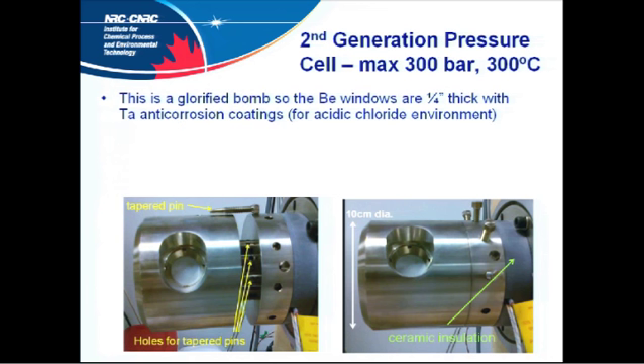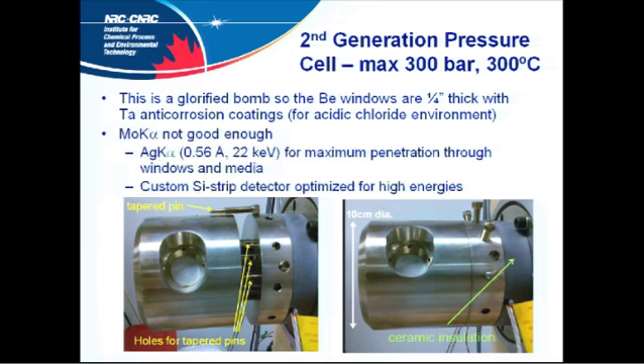Now, this, as I say, is a glorified bomb. This is a new one. 300 bar, 300 degrees. This thing's heavy. This is where you start getting into size and weight constraints. This thing's about 10 kilograms as a full thing. So there's actually quite a lot of weight hanging off here. Moly's not good enough, so you're really having to go to silver at this point.